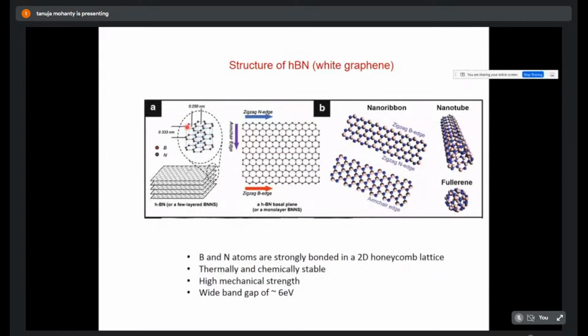Initially, HBN was used particularly as a substrate to grow graphene material, because they have mutual lattice compatibility. But later on, these materials became very useful for quantum optics, so those materials are now being studied. This material can be in the form of a zigzag nanoribbon, or a nanotube, or a fullerene. Well-studied fullerenes and nanoribbons are from graphene, but here these materials can also form nanotubes, and hexagonal boron nitride can form them too. The B and N atoms are strongly bonded in a 2D honeycomb lattice, thermally and chemically stable, with a wide band gap of 6 eV. So why is this band gap so important?